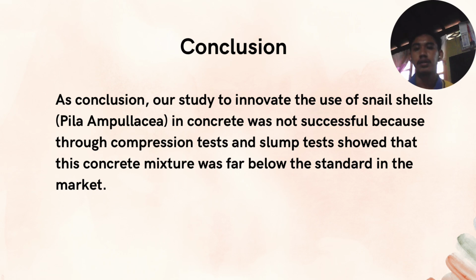Conclusion. As a conclusion, our study to innovate the use of snail shell Pila Ampullacea in concrete was not successful, because the compression test and slump test show that this concrete mixture was far below the standard in the market.